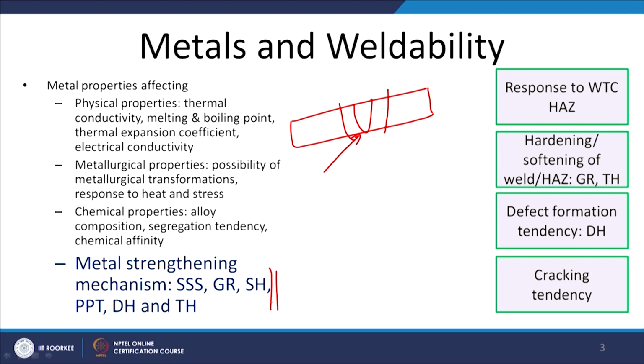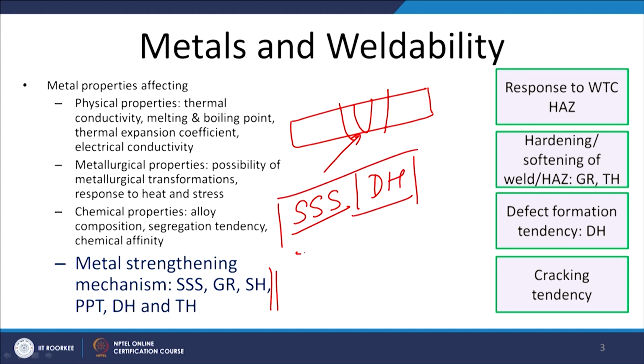Just to elaborate a little bit here, the metals designed for required strength through solid solution strengthening and dispersion hardening, these two types of metal systems are not much influenced by the weld thermal cycle in the heat affected zone. But certainly the properties of the weld metal are affected, because the weld metal is an as-cast structure, and it will certainly have lower properties as compared to the respective base metal properties. However, the effect of the weld thermal cycle on the heat affected zone properties will be very limited.